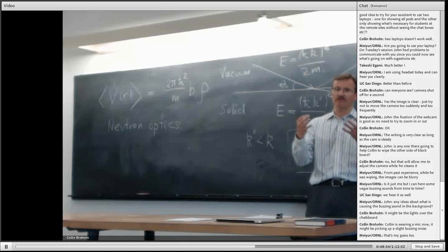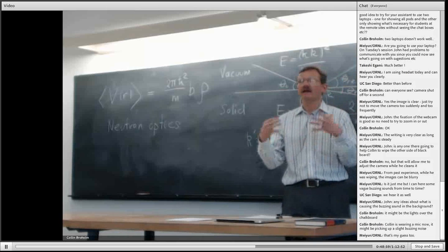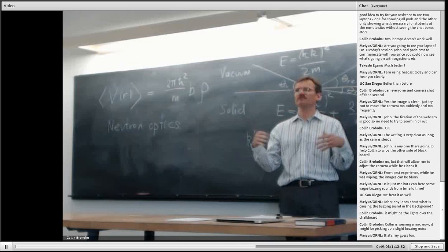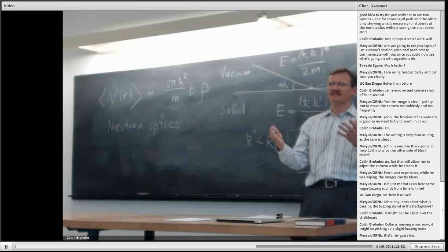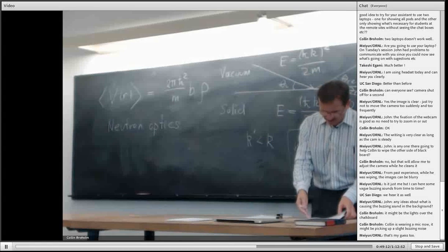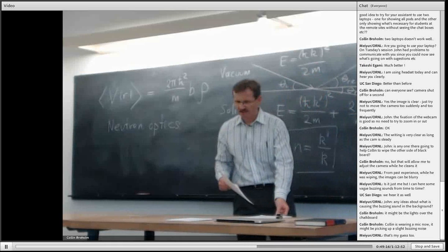And so, for example, with cadmium, which I did mention, illuminated with neutrons, you get a very hard gamma radiation coming off from the cadmium. So you do absorb the neutron beam, but you create instead a radiation hazard from this hard gamma radiation. So there are quite some considerations that come in as we begin to consider the use of absorbing elements in our experiment.